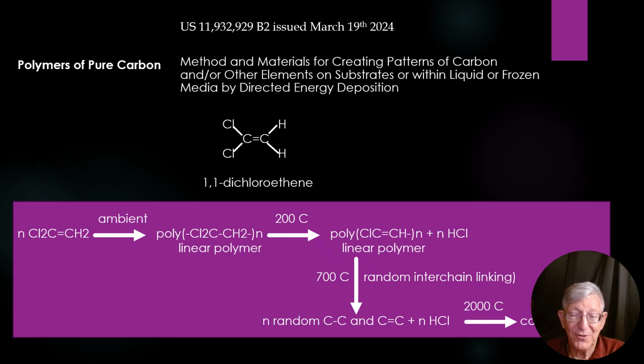Now, what we're trying to do is we think there's some fairly simple ways to try to control this second step where we say 700 degrees C. We think we can mitigate the premature or uncontrolled cross-linking amongst these chains. And hopefully we can figure out a way to either make graphene or carbon nanotubes in a fairly straightforward way. And that is sort of one of our research goals.